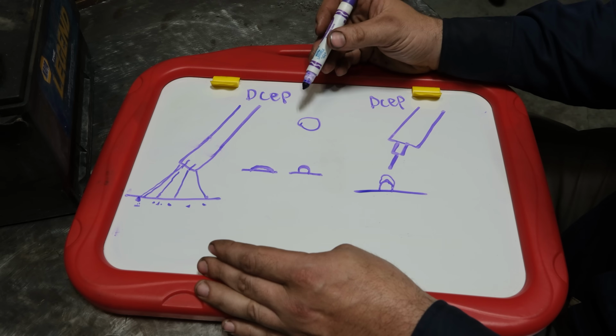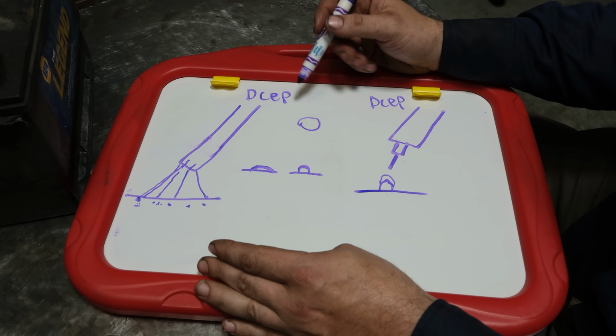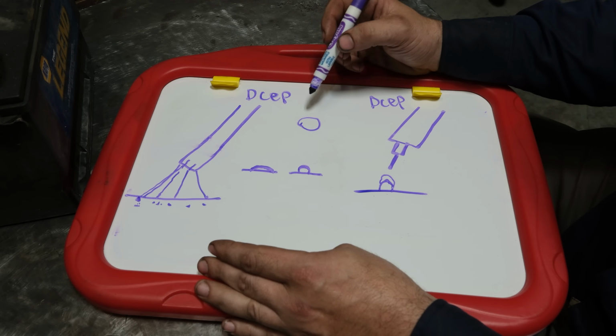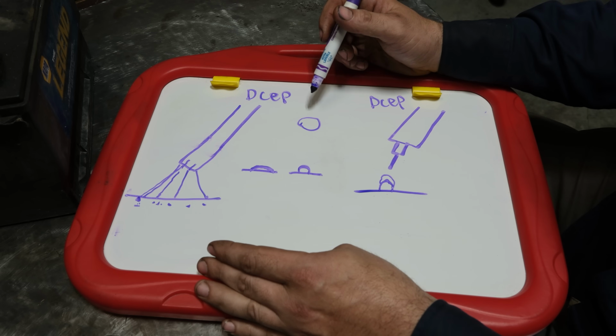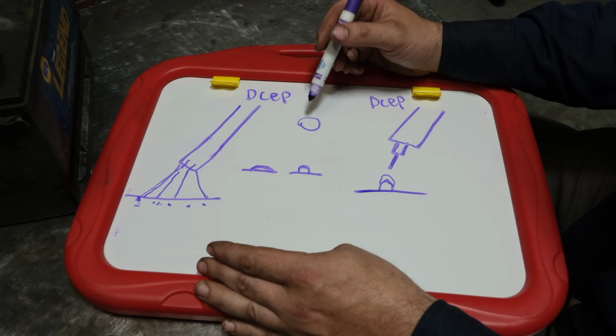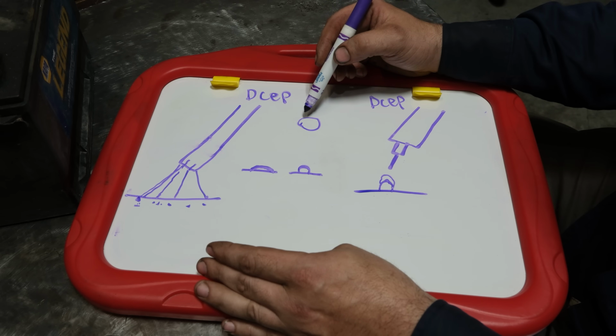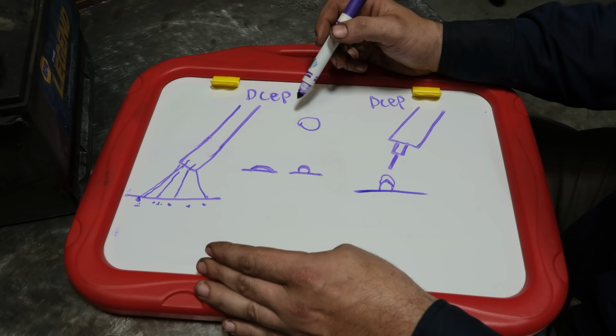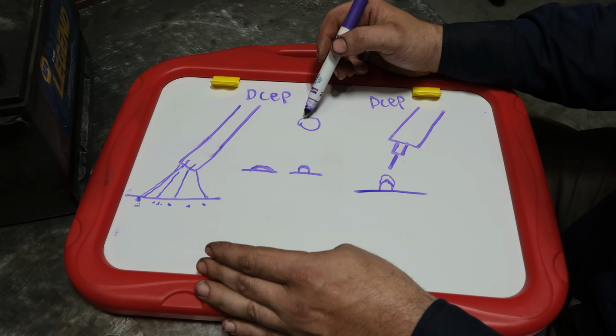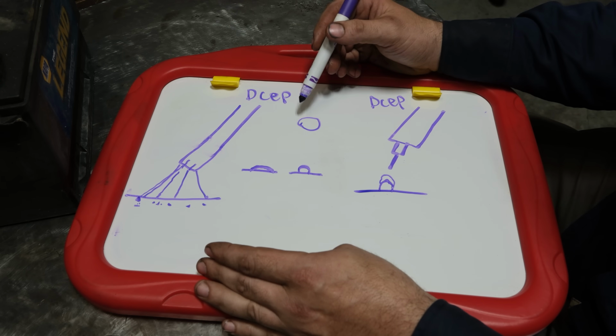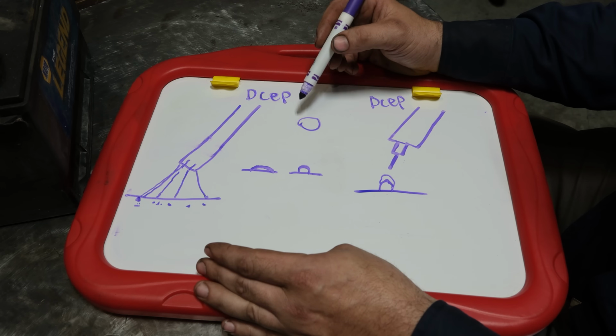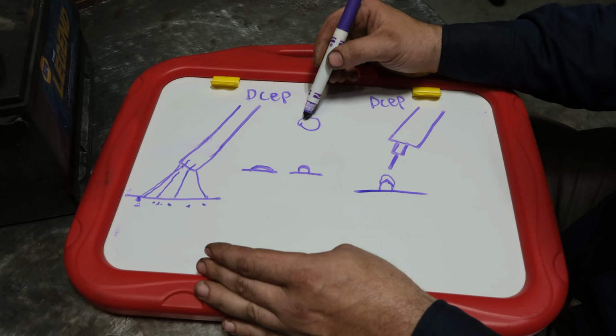With dual shield, where you're running a flux cored wire and shielding gas, that is not an issue because you actually run that on EP. I think the reason it's not an issue is twofold. One, I believe the wall thickness on dual shield is probably a little bit thicker than self-shielded. Self-shielded needs a lot of flux inside in order to produce shielding gas and protect the weld. Well, dual shield, because you're using a separate shielding gas, you could probably use a thicker wall wire with less flux inside. So that's part of it.